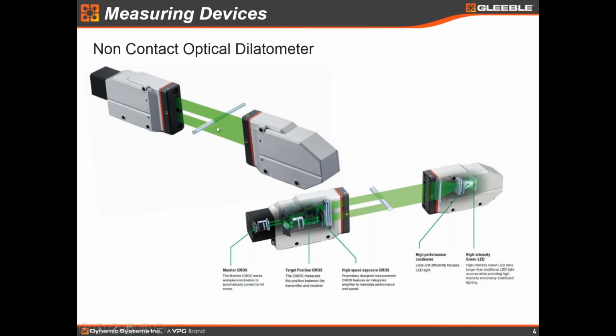Now, I would like to point out that we do dilatometry a little differently than most other manufacturers in that we usually measure the diametral change of a round sample. A lot of other machines are configured to measure the length change of a sample, and there are reasons that we do this, and I'll get into those in a little bit, but just keep in mind throughout this presentation that we do measure the diametral change typically when we're doing dilatometry in a Gleeble, and that is a little bit different from most of the other equipment that is out there.